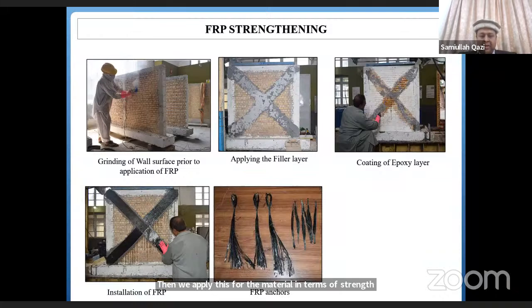And as the major flaw in case of FRP used in the construction industry, if you just overlay it on a structure, we can have only 55% efficiency of the material that we use. So in this case, we have techniques.